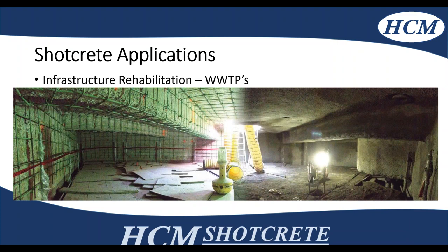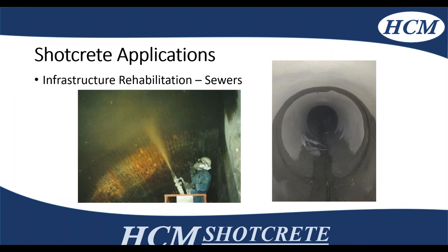This is an example of a wastewater treatment plant in Barrie that we rehabilitated. This tank was an anaerobic digester that had issues with microbial attack. We went in, chipped and prepped the surface, and added an admixture to the shotcrete to fight against the microbial attack. We rehabilitated this with a gun finish — also dry mix shotcrete, overhead and vertical. It can also be done in sewers; on the left-hand side they're rehabilitating a brick sewer, meshing it and shooting it to ensure structural integrity.